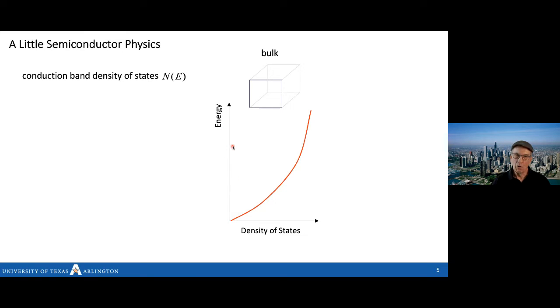So for a bulk semiconductor, the density of states starts at zero. Well, zero energy is actually the lower edge of the conduction band, and there aren't any states in the gap. So as we go up in energy from that, we have this parabolic density of states. That just tells us where there are states, not whether they're occupied. So to find out if the states are actually occupied, we take the density of states and multiply it by the Fermi function, which is this blue line. And the product of these is the density of occupied states. Well, that's this purple region here.